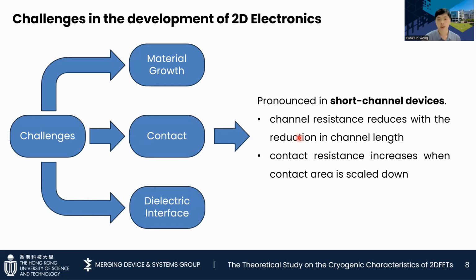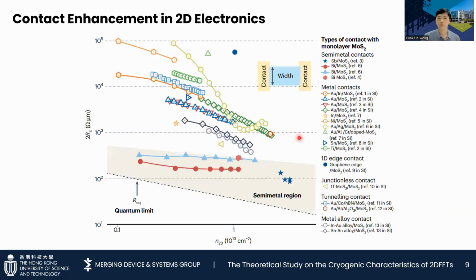The channel resistance is reduced and approaches the ballistic limit, so electrons travel the channels with minimal scattering. However, contact resistance increases when the contact area is scaled down. The high contact resistance results in substantial voltage drops at both drain and source regions, which limits the transistor's driving ability. This picture shows the progress made in minimizing the contact resistance of 2DFETs. We can see that at the current stage, through the introduction of semi-metal contacts, researchers have successfully minimized the contact resistance and approached the quantum limit.